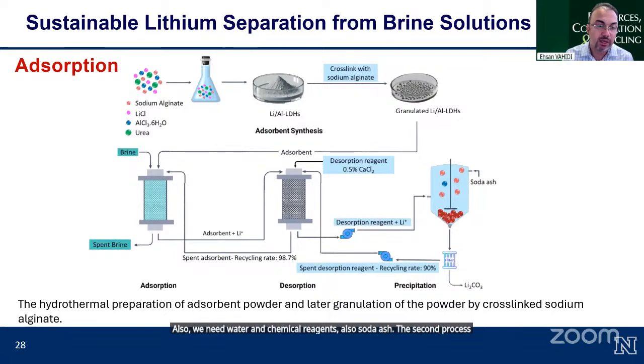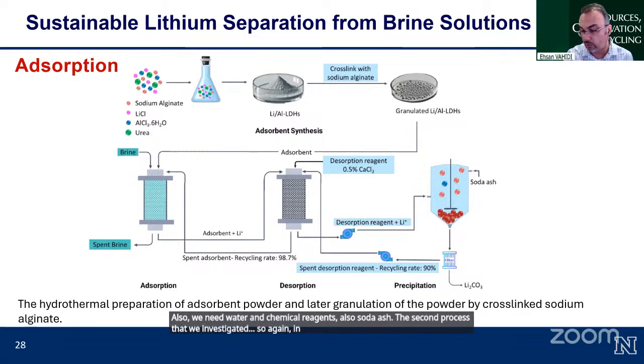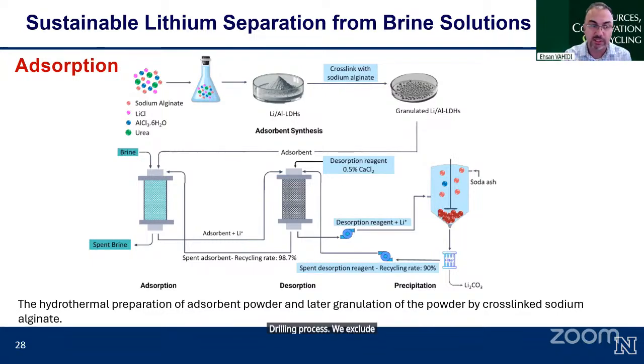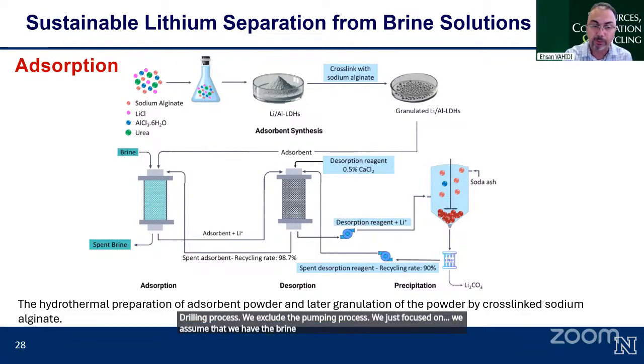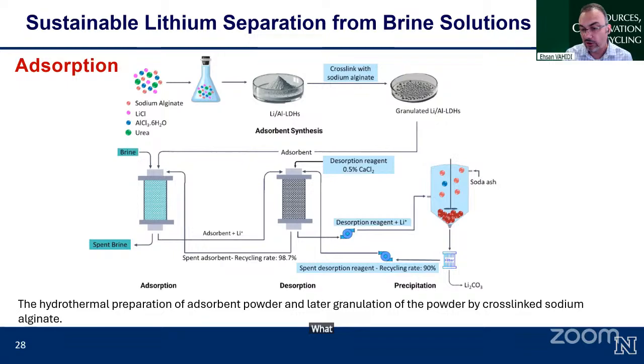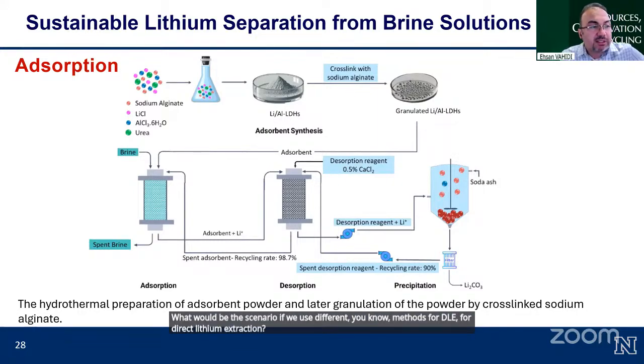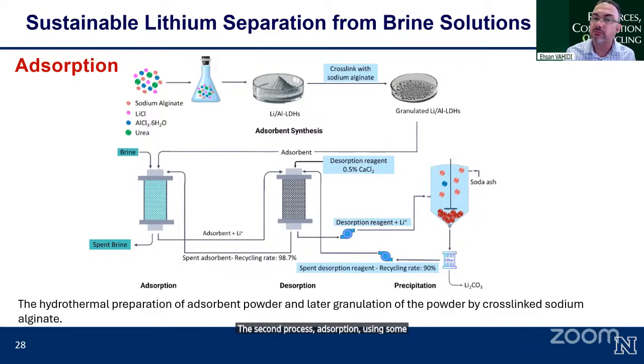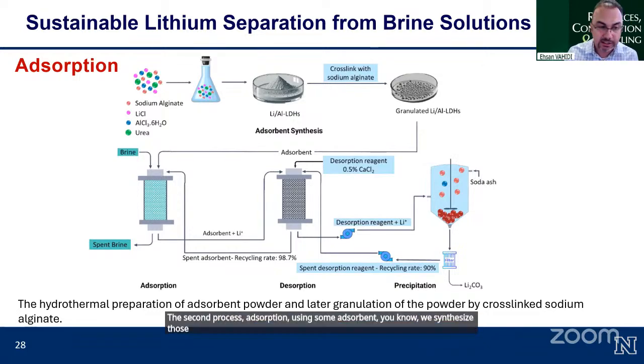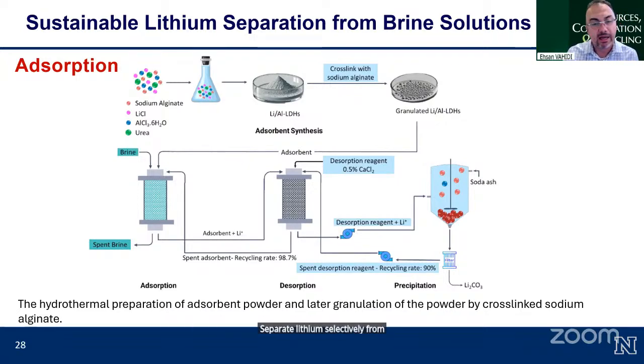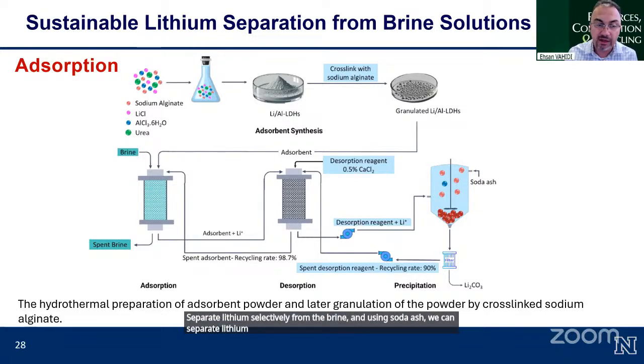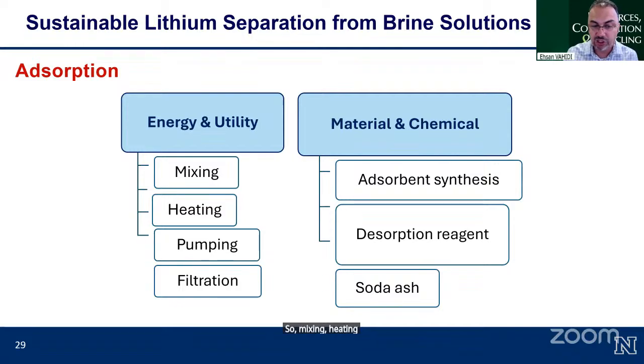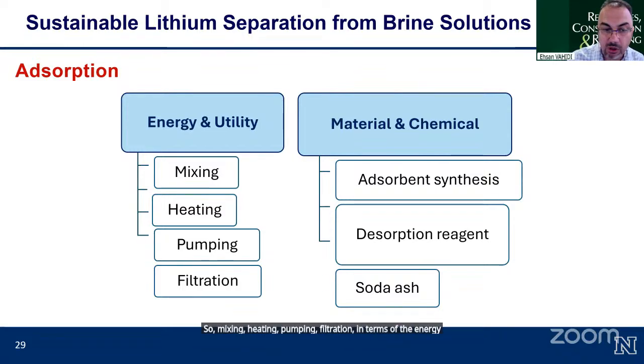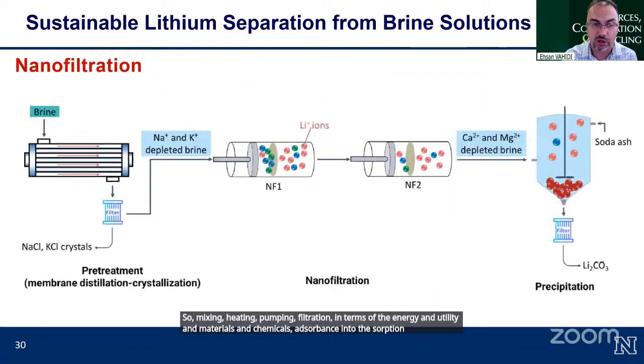The second process that we investigated, again, in this study, we focused just on the separation process. We excluded the drilling process. We excluded the pumping process. We assumed that we have the brine and would like to separate lithium from it. What would be the scenario if we use different methods for DLE, for direct lithium extraction? The second process is adsorption, using some adsorbent. We synthesize those adsorbents. We can separate lithium selectively from the brine, and using soda ash, we can produce lithium carbonate equivalent. So mixing, heating, pumping, filtration in terms of the energy and utility, and in materials and chemicals, adsorbent synthesis, desorption reagent, and soda ash.